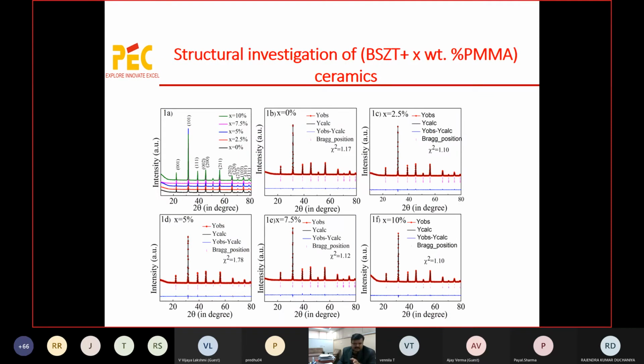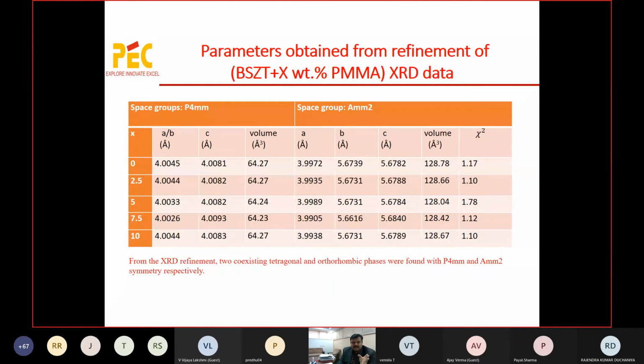So she prepared 5 different samples. The first figure shows all the XRD patterns, and the rest of the figure shows the XRD patterns of different compositions with Rietveld refinement. And you can see that in the Rietveld refinement, the observed chi-square values are less than 1.5, which is a good signal, but except this x is equal to 5%. Otherwise, for all, she obtained a chi-square value less than 1.5. That shows very good fitting. So these are the parameters she observed from the Rietveld refinement.